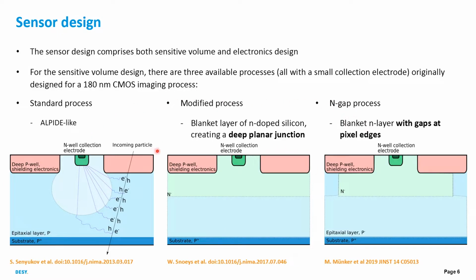And you can see sketches of them here. So the standard process is Alpide-like, where we have a small collection electrode and then depletion grows from the small collection electrode. This means we're undepleted under the p-wells. Basically, charges move by drift in depleted regions and by diffusion in undepleted regions, and it's often desirable to have as big a depleted region as possible.